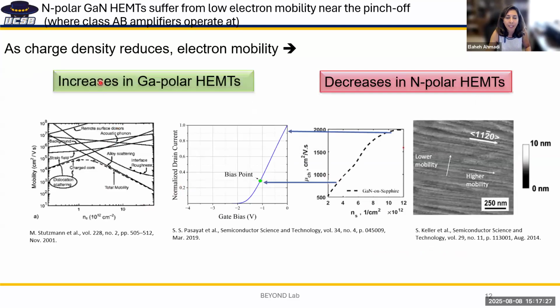But another thing that we had seen in nitrogen polar HEMTs, even though these great results have been demonstrated, and better performance at higher frequencies has been achieved by nitrogen polar, is that in gallium polar, as we start applying a negative gate voltage and we are pinching off the channel, the mobility keeps increasing. And near pinch off, the mobility is actually very high, and then at very low charges, it drops a little bit. In nitrogen polar, we always saw an opposite trend.